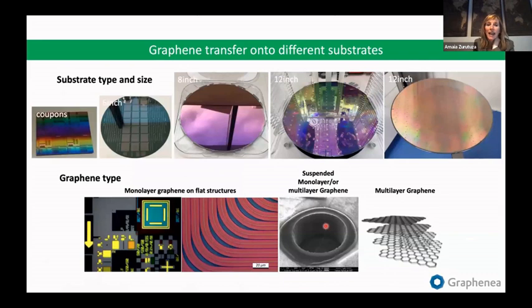In principle, you can transfer graphene onto any substrate. It can be a flat substrate, only silicon with silicon dioxide. It can have metal contacts at the bottom, or waveguide-containing wafers. These are some images of these substrates, actually. We could also suspend graphene over cavities. So this transfer process has quite a lot of versatility.